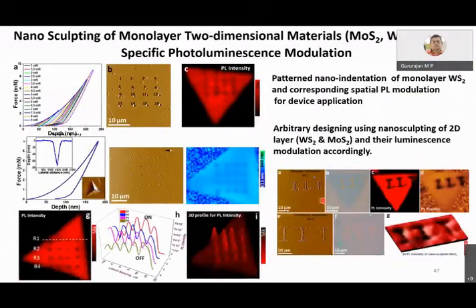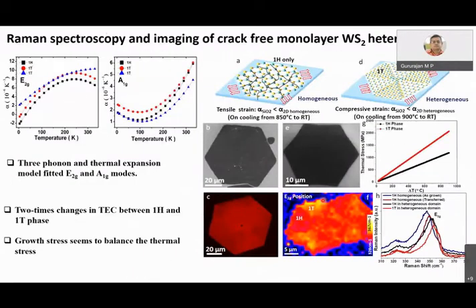So yes. The 1H, I can understand why it is showing hexagonal, but why is the 1T also showing similar facets? In this case, the 1T is not fully grown. It's actually nucleating and growing within the 1H phase. Initially it was 1H, so it was hexagonal, and the T is coming up. The only thing is we are able to achieve this during the CVD growth itself.